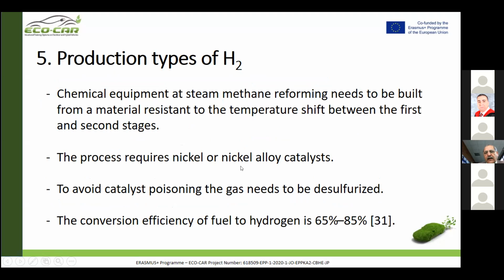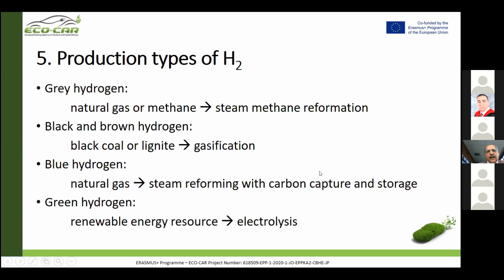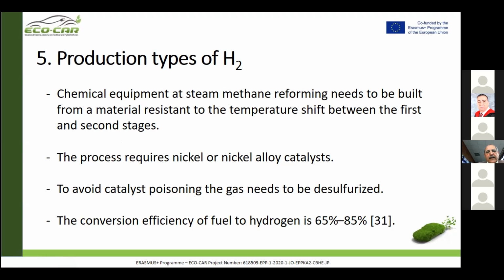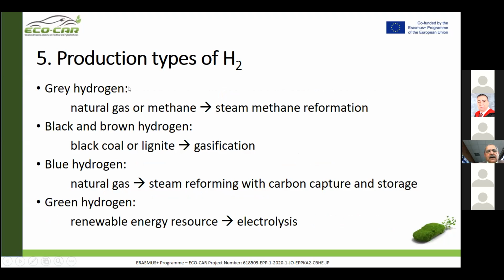The process requires nickel or nickel alloy catalysts to avoid catalyst poisoning. The gas needs to be desulfurized, as it is not allowed to have sulfide. The conversion efficiency of fuel to hydrogen is about 65 to 85 percent, according to the process parameters. So that was only an example, and for the other kinds of hydrogen production, I will